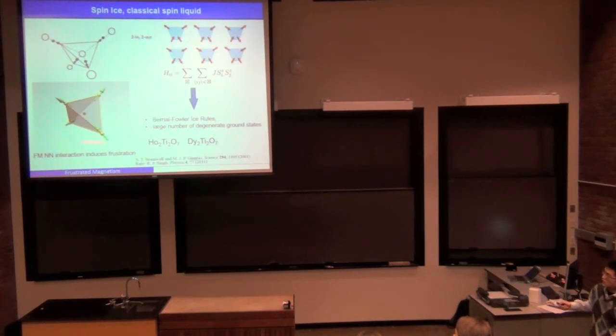So as a result, the ground state of a single tetrahedron has this so-called two-in, two-out configuration. So there will be two spins pointing into the center, and two spins pointing out of the center. But since there are four spins on this tetrahedron, there is also a huge number of ways this two-in, two-out state can be realized. It turns out for a single tetrahedron, there are six different possibilities of this two-in, two-out state. As a result, there is also a huge number of degenerate ground states.